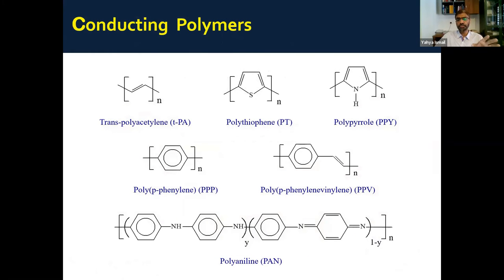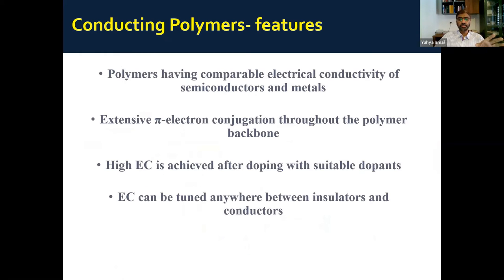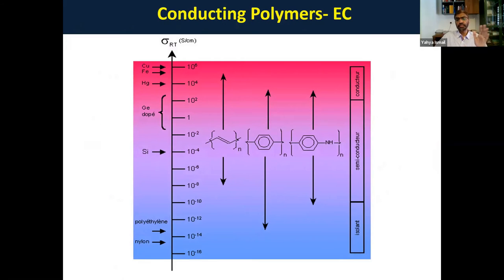The most important aspect of this material is that they have an extended pi electron conjugation, and their electrical conductivity can be tuned anywhere between insulator and conductor. If you want a conductivity of 10 to the power minus 8, you can make a polyaniline of 10 to the power minus 8. If you want 10 to the power minus 2, you can make that. If you want a polyaniline of conductivity 10 to the power 2, you can make it, because unlike metals, the specific conductivity can be tuned anywhere between insulators and metals. That's why they are termed synthetic metals.